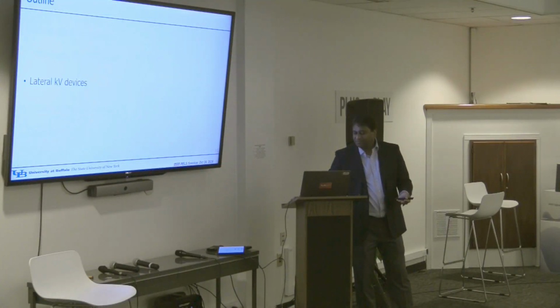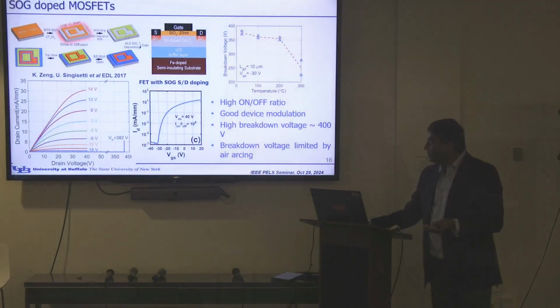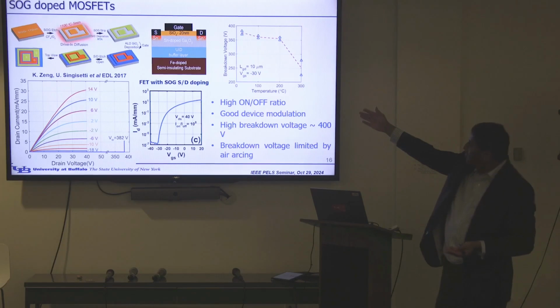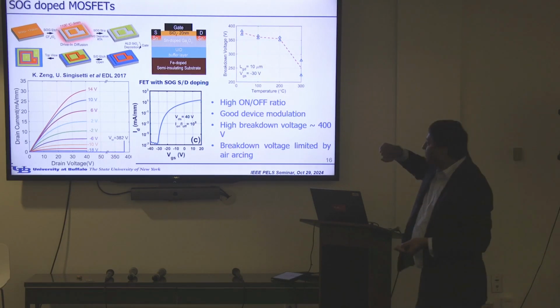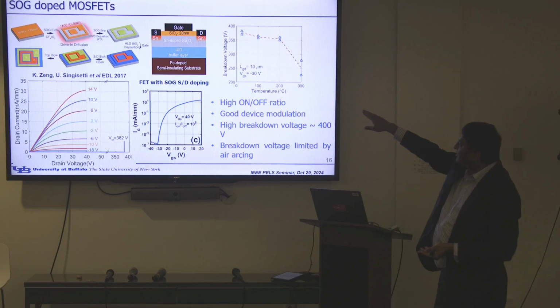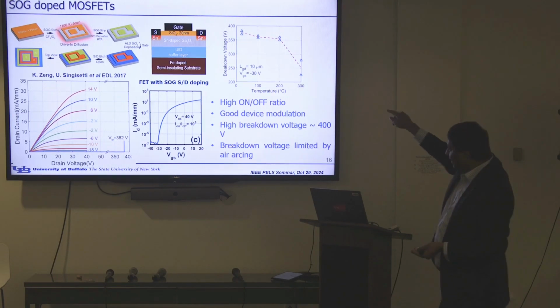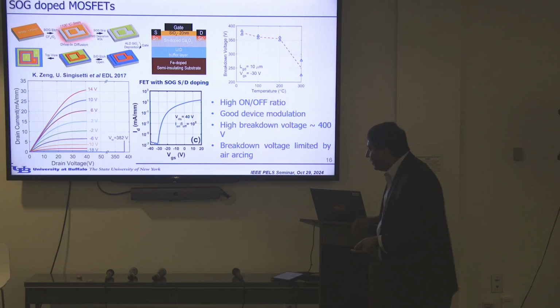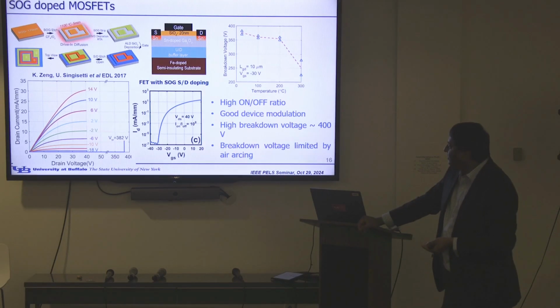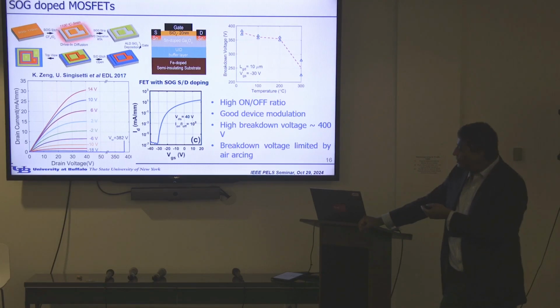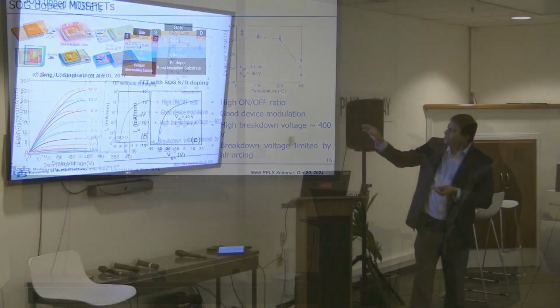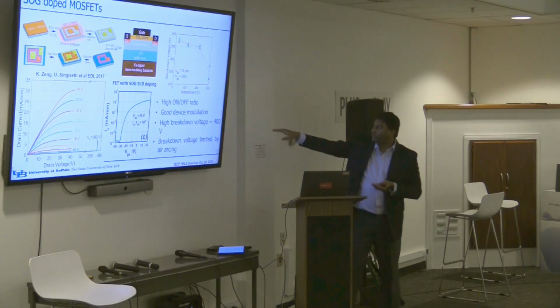So now I'm going to switch to talk about the work done in our group over the last few years. The first device we made, you can see in the center there, is a standard textbook kind of device. Silicon dioxide gate dielectric, source and drain done by spin-on dopant, and then you can see on the bottom left there, you get a good gate modulation. Breakdown was 382 volts. On-off ratio is pretty good at 10^8. And these devices were breaking down close to 400 volts.